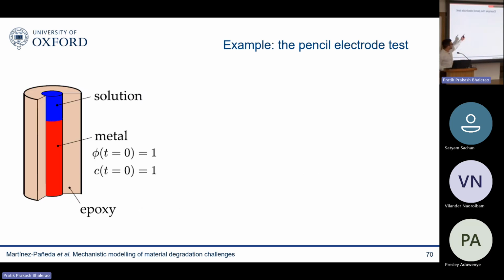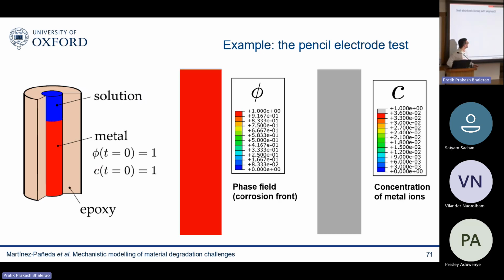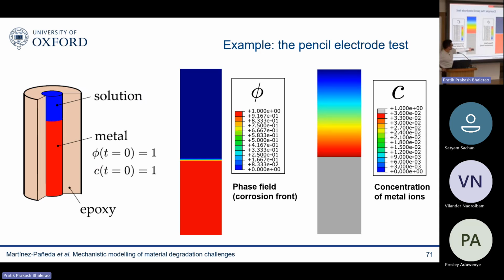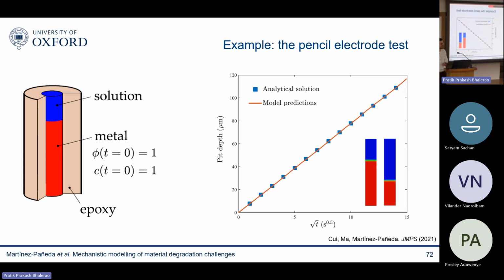So this is a pencil electrode test. This is a simple 1D example where you basically have corrosion of the metal happening in a uniform way. And you can see an example. So this is the model showing how the corrosion front evolves in time. And this is the distribution of metal ions, which is the highest at the interface. And then they just go away into the electrolyte, basically. And the good thing about this very simple 1D problem is that you have an analytical solution, and a lot of experiments that we can also validate against. You have an analytical solution for the case of diffusion control corrosion. And you can see that the model seems to agree quite well.